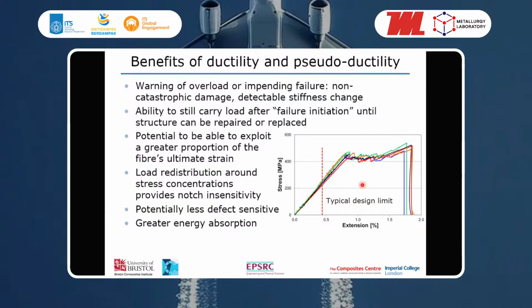Things like pressure vessels for storing carbon are really designed on ultimate strength and would not benefit from this, because we're actually not exploiting the full strain of the carbon. But if you look at aircraft structures, they're never designed up to the full strength of the carbon fibers, because one of the largest concerns is notches. In aircraft structure, you have many notches, so they're designed to notch strength, and particularly under hot, wet conditions where carbon composites can be very susceptible to damage.